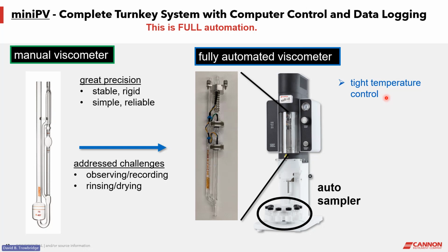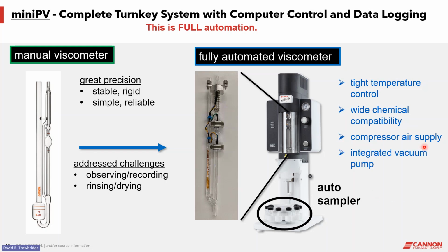It has tight temperature control, 0.01, 0.02 degrees C, plus or minus. Then we also have a wide chemical compatibility because this instrument is constructed of Teflon. We also have an integrated compressor as part of the instrument. We also have part of the instrument an integrated vacuum pump. These are the tools for controlling the solvent during the washing and the drying process. All these features together now have added to the advantages by making a rapid analysis and a continuous operation.